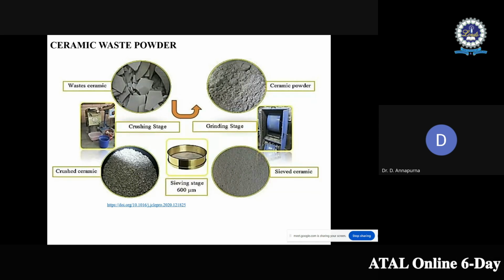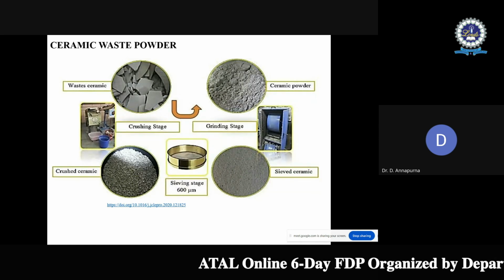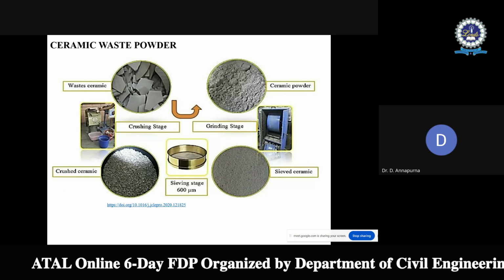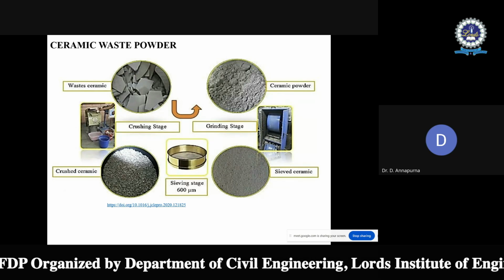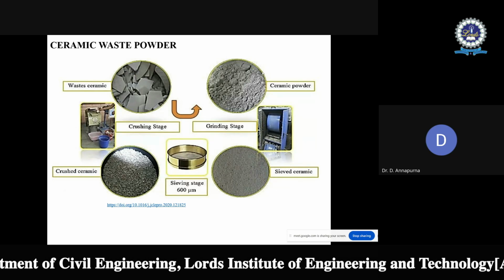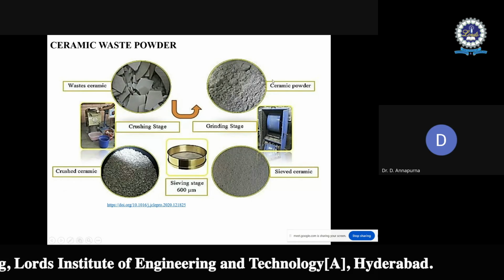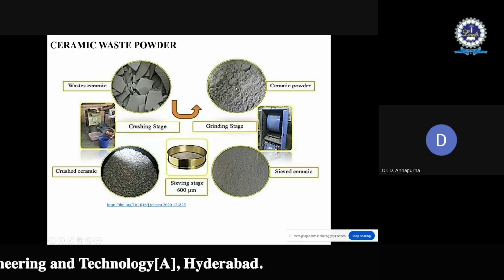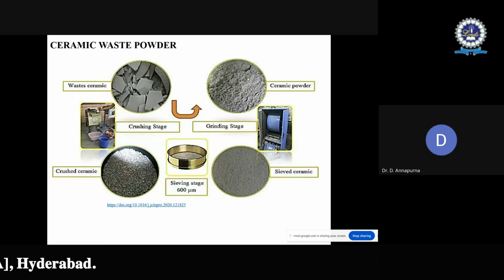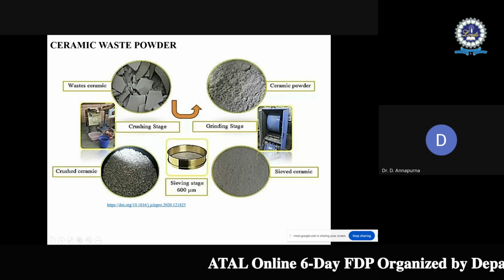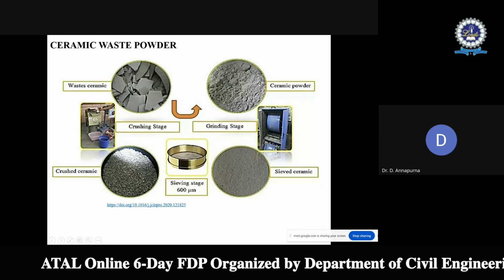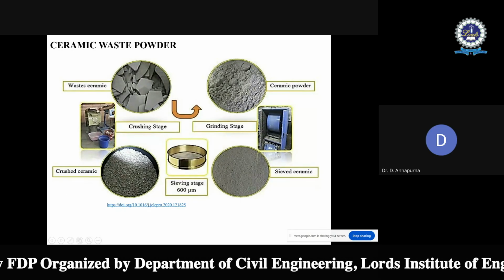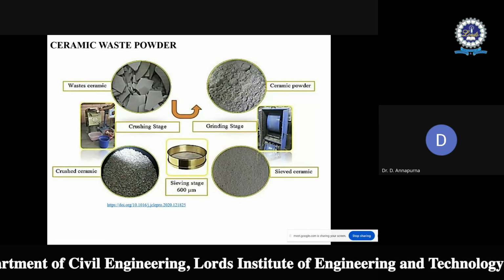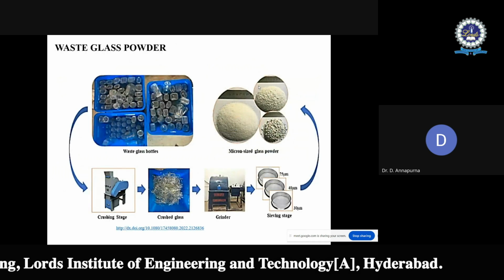Then ceramic waste powder. From the ceramic industries, when the ceramic waste is collected, it is crushed into small pieces, then ground to get the fine powdered form, and we get ceramic powder. Again, this is rich in silica and alumina, and in between it is sieved to get the desired size. It is rich in silica and alumina, so it can be used as a best source material in the production of geopolymer concrete. Waste glass powder.